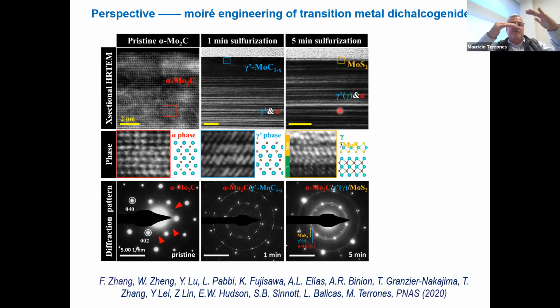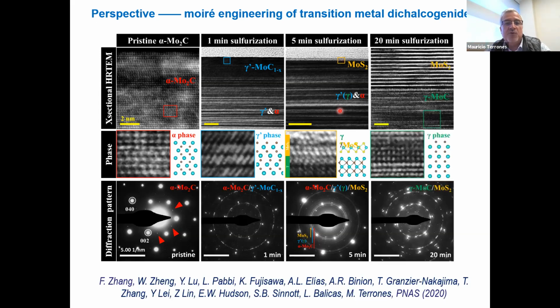So you have a sandwich heterostructure of all this. And when you do it for 20 minutes, now you have 2 peaks, and you have the gamma moly carbide, which is the most stable one. So you transform your alpha moly carbide into gamma moly carbide, and then you have this moly sulfide as well. So this is very nice. And what is interesting here is that this 1 minute, this metastable state, is very interesting. I will show you why.